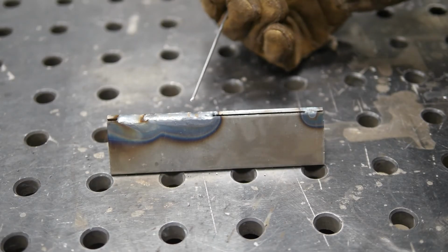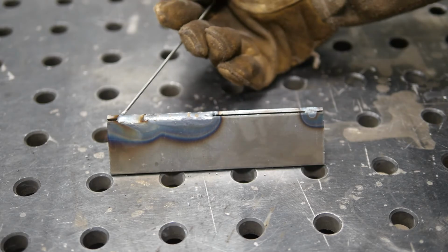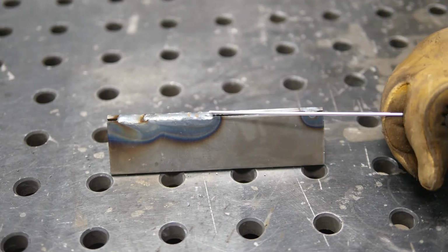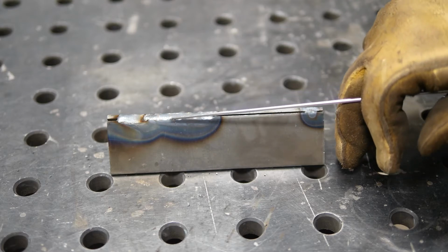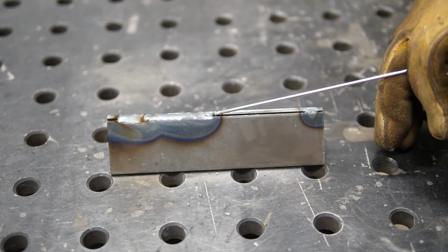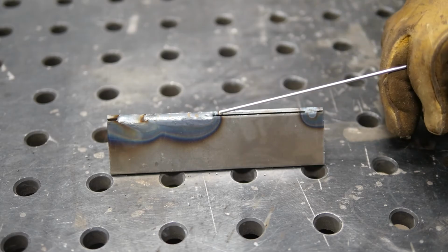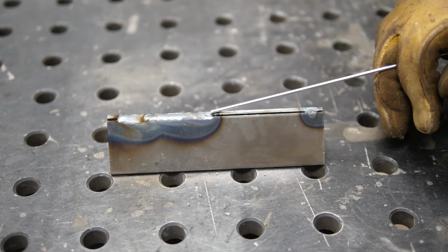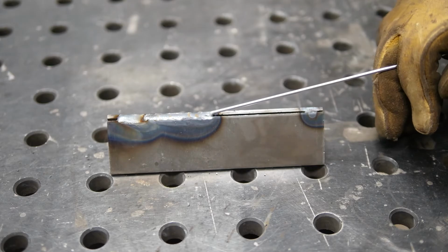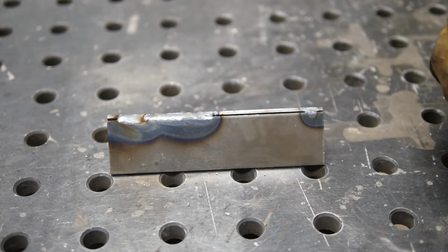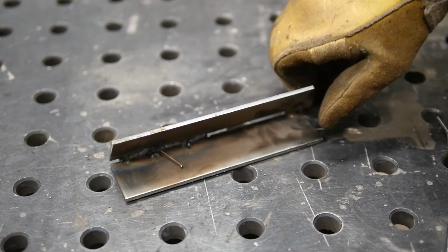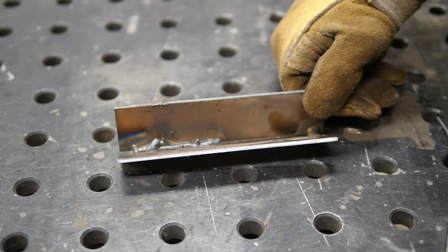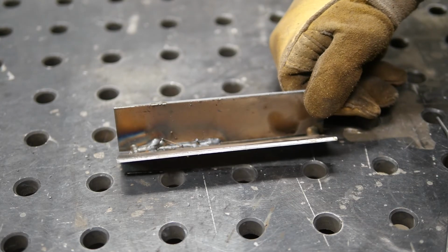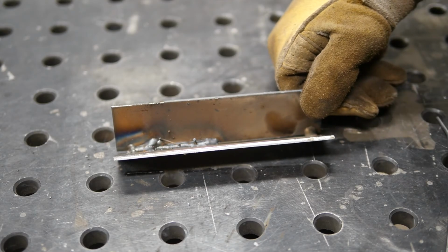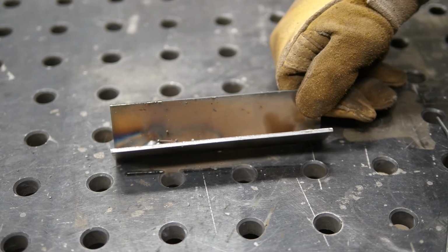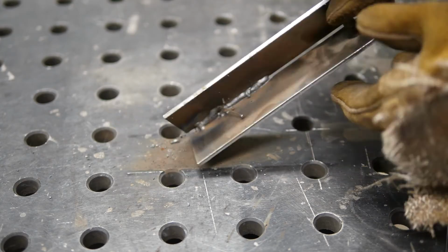So that was 130 inches per minute. You can tell from 240 to 130, we got less penetration and we didn't dump as much wire in there and didn't come as close to blowing through as we did there, but the leading edge of the puddle was still a little unstable. There's a few times I had to work backwards to save it from popping through. And if we look on the underside here, you can see it popped through one time and there's quite a lot of penetration there. So even still, I'm going to turn the machine down further to get a better looking weld here.